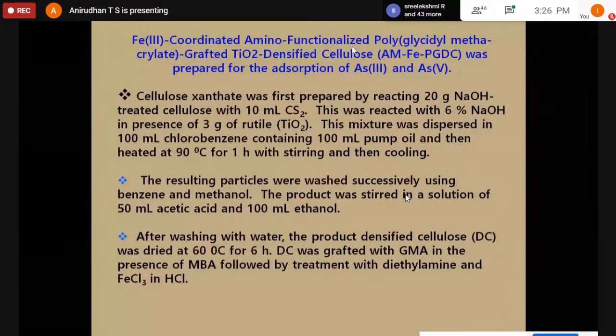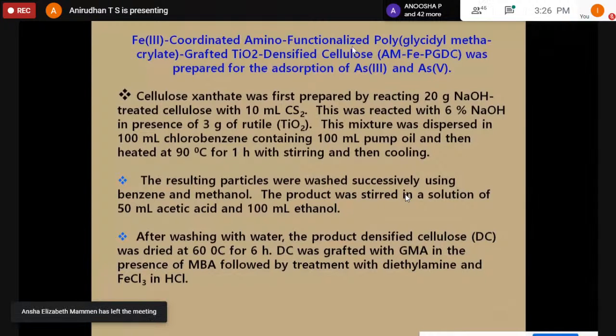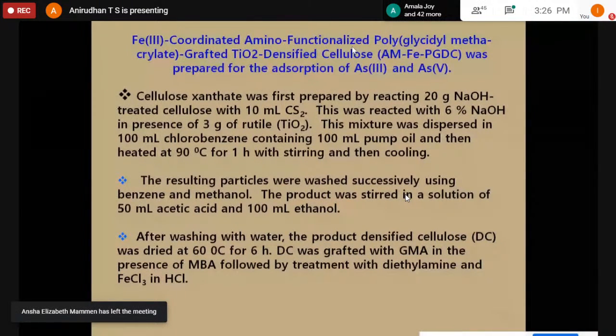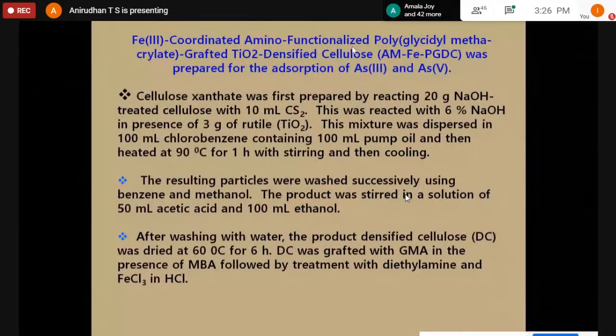So how do you prepare this? It's very complex in nature. First you convert the cellulose into cellulose xanthate. How do you prepare cellulose xanthate? Very simple, I think. Cellulose xanthate was first prepared by reacting 20 gram sodium hydroxide treated cellulose with 10 ml carbon disulfide. Once you treat with carbon disulfide in presence of sodium hydroxide, your product is cellulose xanthate, and this cellulose xanthate is further treated with rutile.